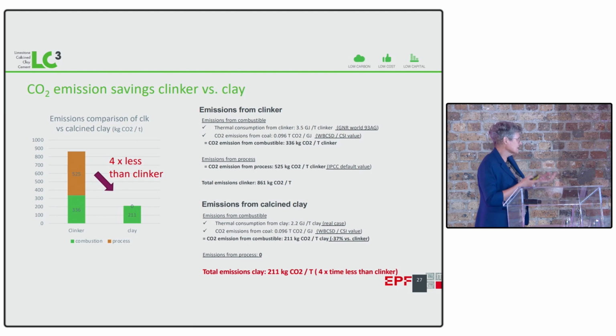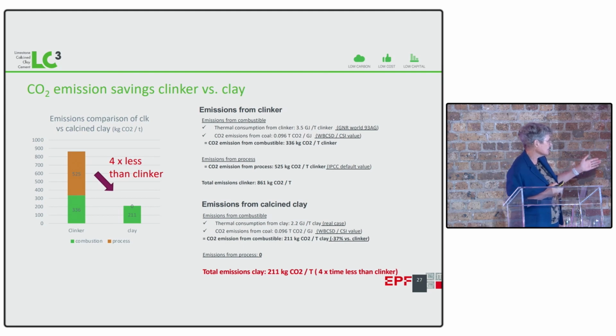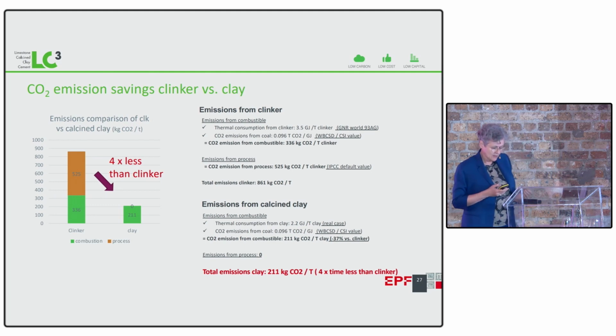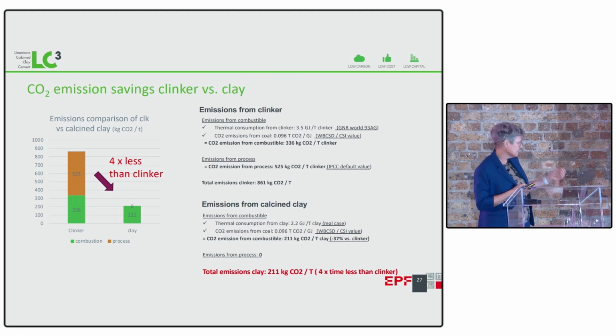And why does this save CO2? Well, here's a detailed analysis of the energetics for producing calcined clay. These are figures taken from a real project. They're going to be slightly different in all the different projects, but here in this version you see that you've got emissions that are 4 times less than clinker. So for every bit of clinker you take out of your cement or your concrete, you've got 4 times less emission, and then you've also got the limestone on top, which has got effectively 0 emissions.